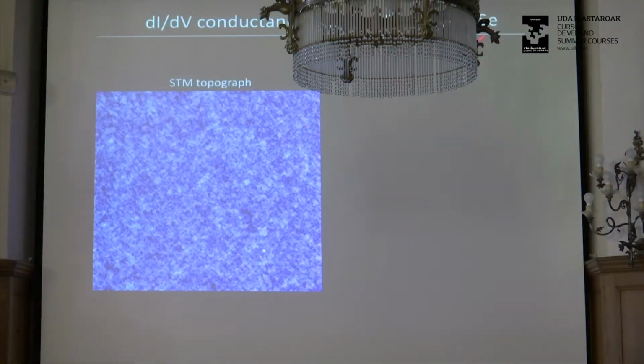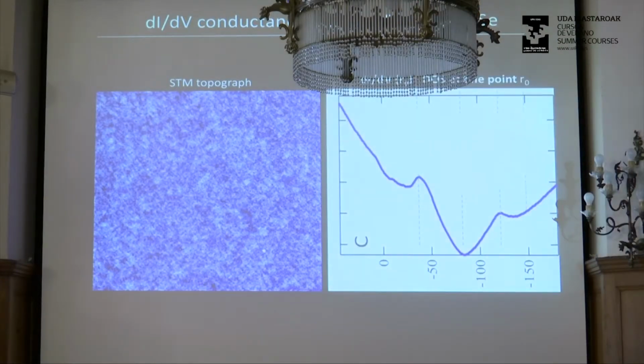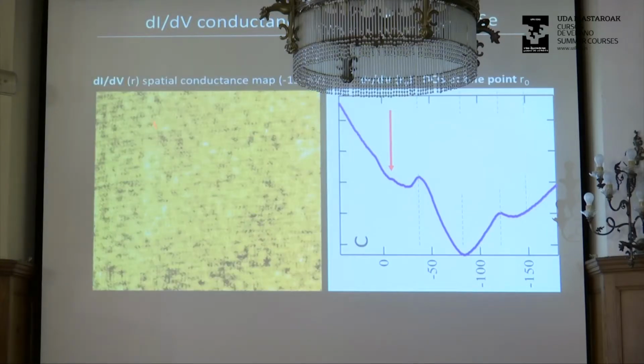Here's the topography on this material. One thing I want to show you is we often take things that are called dI/dV maps. Let's say this is a spectrum at some point here on the sample. What we'd like to do is go to some particular energy, in this case, let's say 15 millivolts, and plot the height, that is the density of states, as a function of position on this surface. So this is an example of a spatial conductance map at 15 millivolts on the same area, okay? These spatial conductance maps can have a huge amount of information on how the density of states at a particular energy is varying with position.